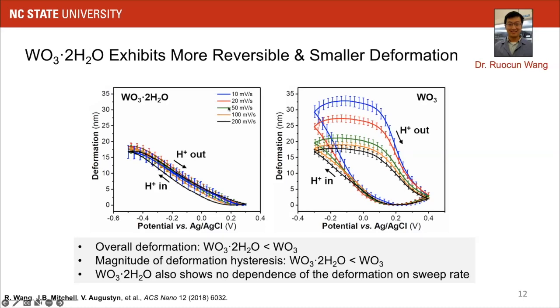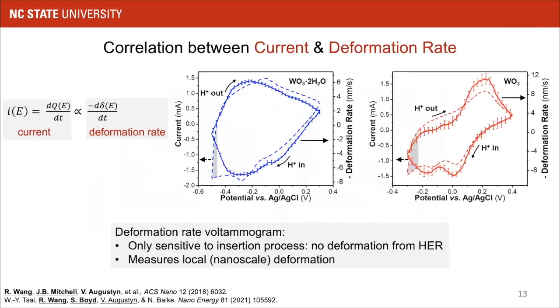And there's also very little dependence of the deformation on scan rate, as protons are cycling in and out of the material. So right away, we see that one of the big differences between these two materials has to do with how stable the structure appears during the proton insertion and deinsertion process.